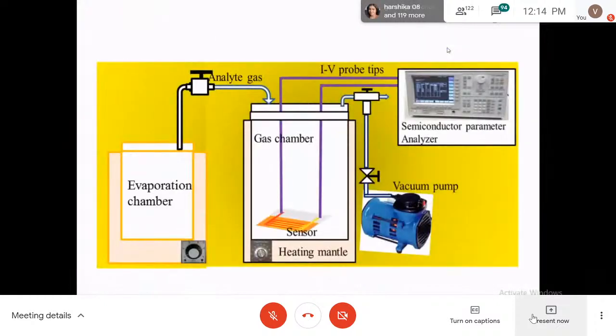So this is the actual experiment setup used for this gas sensing. It is a simple setup. We did not use any mass flow controller to introduce ammonia or ethanol. Instead we use an evaporation chamber. We took ethanol and ammonia as a liquid form and evaporate them in this evaporation chamber. We apply some heat, we set this one as 100 degree, and due to this temperature all the gas evaporates,